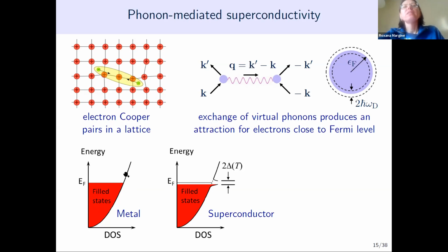While individual electrons are fermions and need to obey the Pauli exclusion principle, Cooper pairs have boson-like properties, and therefore they are able to condense into the same energy level. As a result of this condensation, a gap is formed within the normal valence band around the Fermi level. We can see that the density of states near the lower edge of the band greatly increases to accumulate those electrons that previously occupied states within the gap.